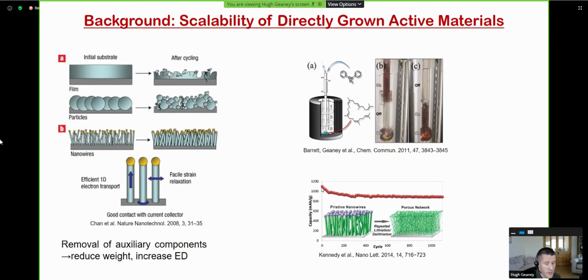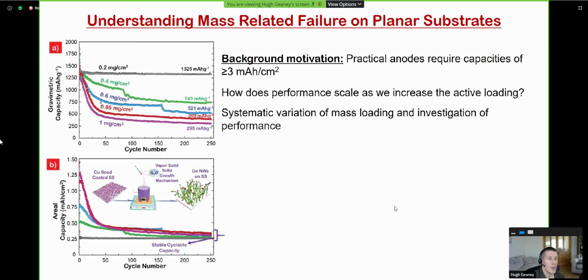There are a couple of really nice findings from the outset with this. Germanium was well known beforehand as a very high capacity material, but in terms of the stability of that capacity, it's absolutely outstanding. He found that after 1,000 cycles, the capacity was almost 1,000 milliamp hours per gram, which is nearly 3 times that of graphite. On the mechanistic side, he found that these pristine nanowires, over the lithiation and delithiation cycles, completely convert into a porous network of active material, which is very stable over long-term cycling.